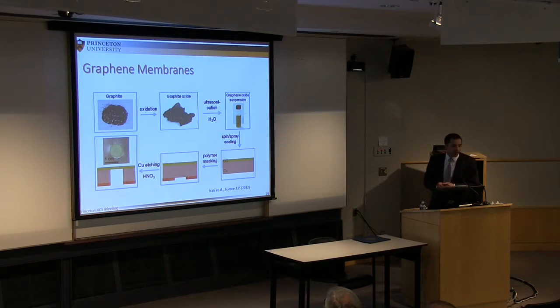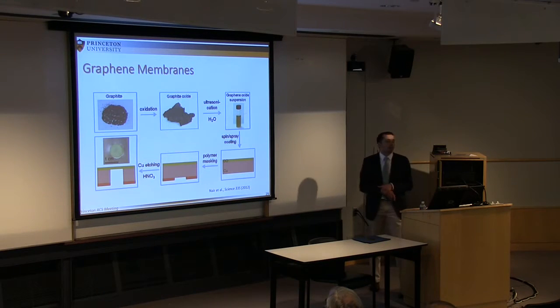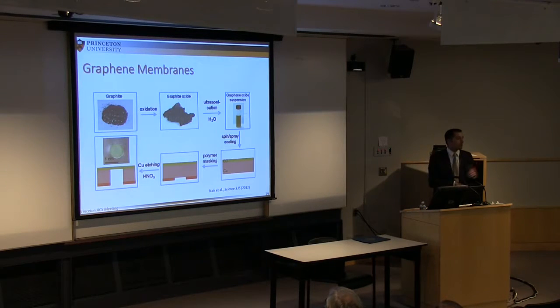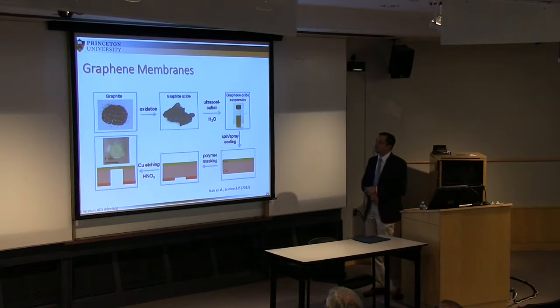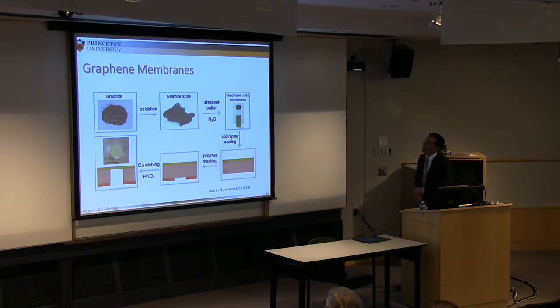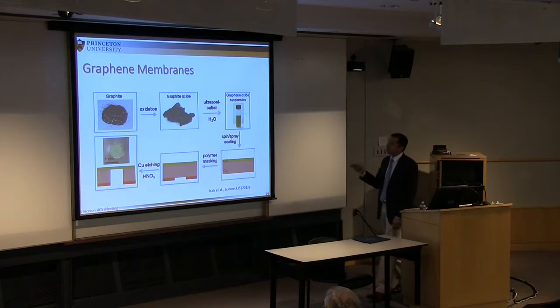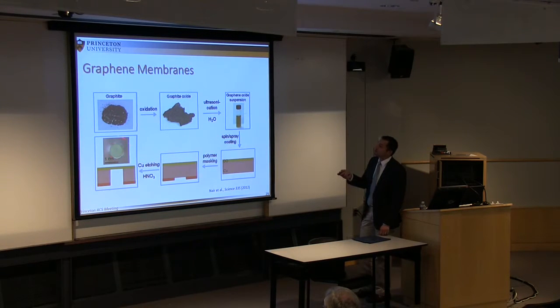So the use of graphene has been in anything you can imagine. I have even seen papers with graphene in cement, so it goes to anything. This is a study done by Geim's group. For this purpose, because they are aware that mechanical exfoliation cannot go too far, they also use the oxidation of graphite to produce a graphene oxide suspension. Then they coat a substrate like copper in this case, and then they make a trench here so that graphene can be accessible after etching with nitric acid. So they end up with this material.